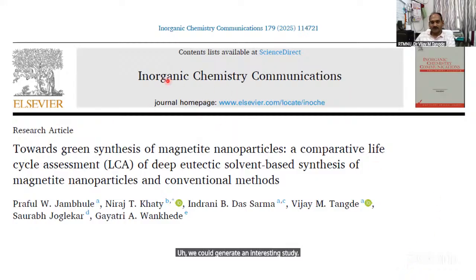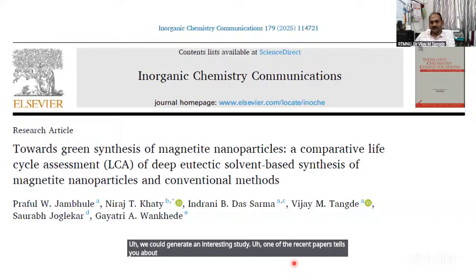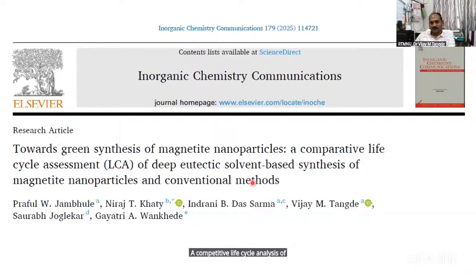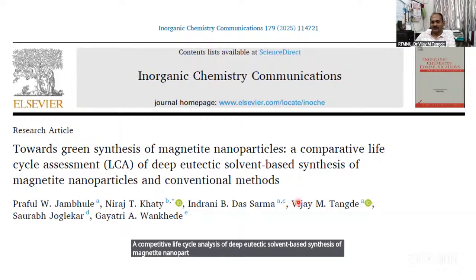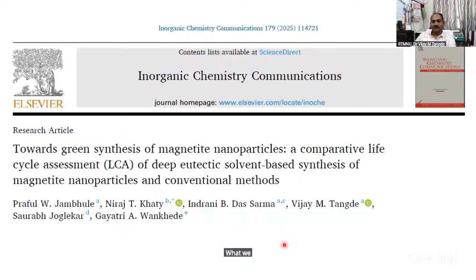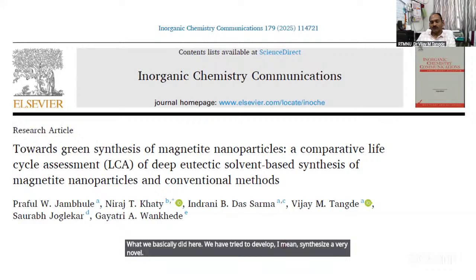One of the recent papers tells you about this, that is, towards green synthesis of magnetite nanoparticles: a comparative life cycle analysis of deep eutectic solvent based synthesis of magnetite nanoparticles and the conventional method. What we basically did here, we tried to develop and synthesize a very novel deep eutectic solvent of choline chloride along with chloroacetic acid. This is what we have taken.